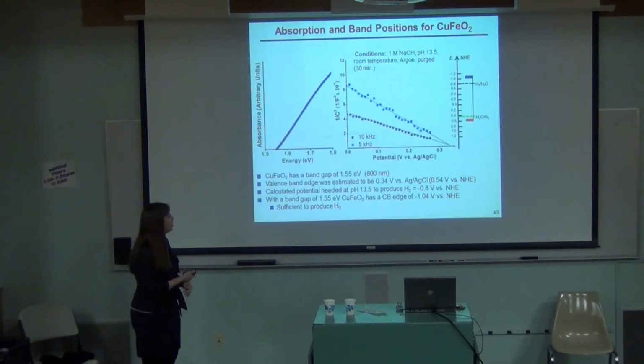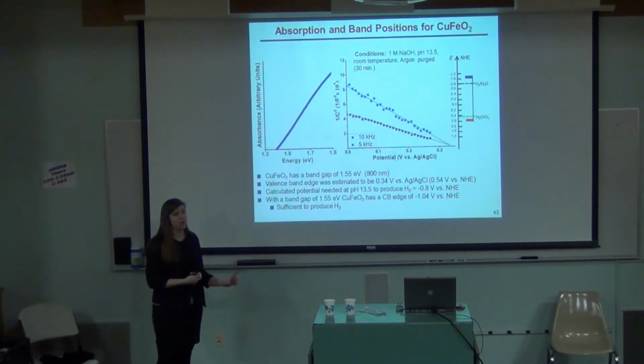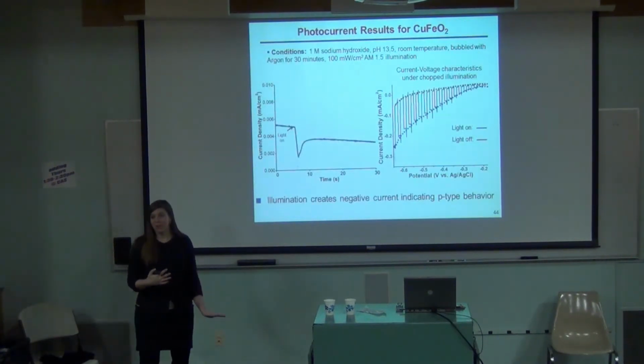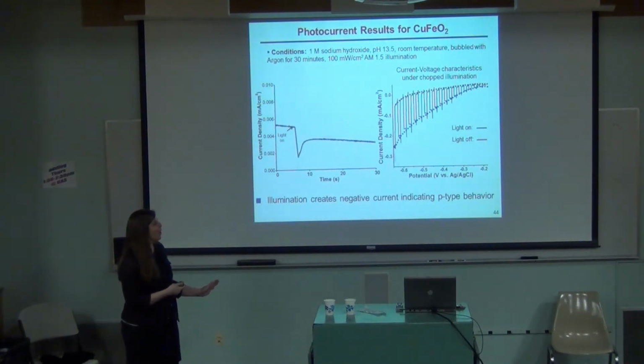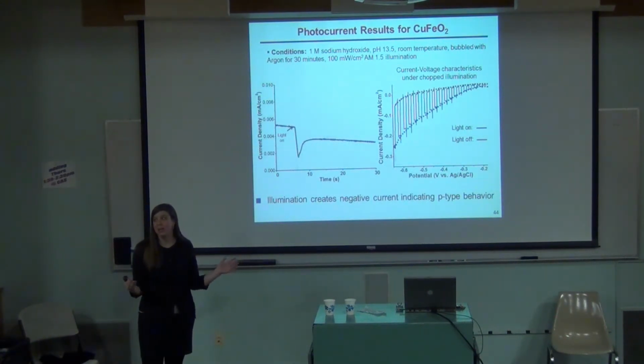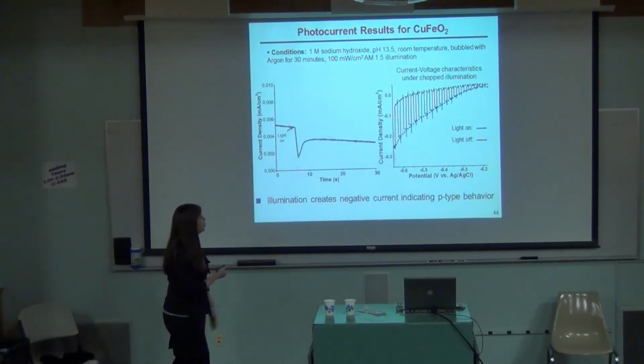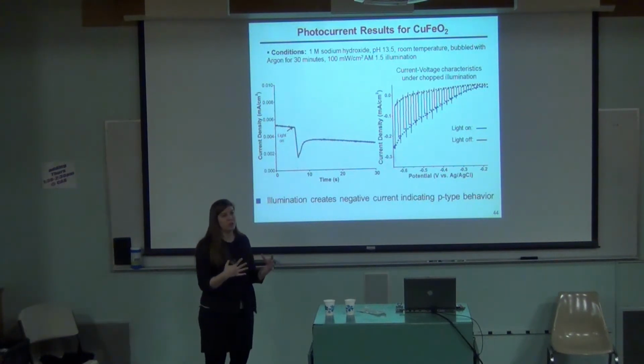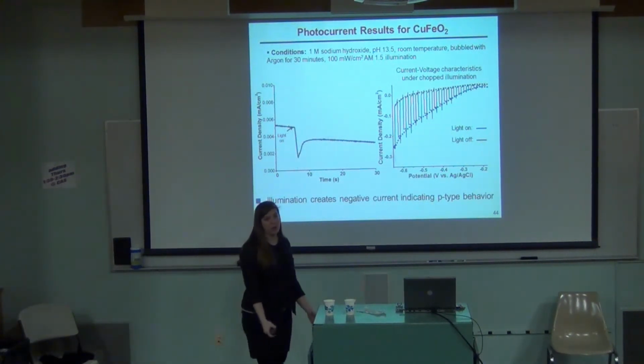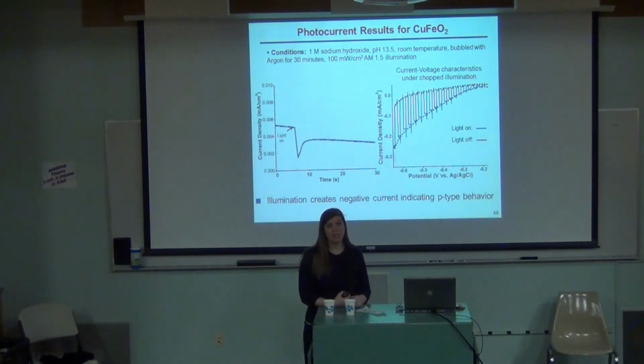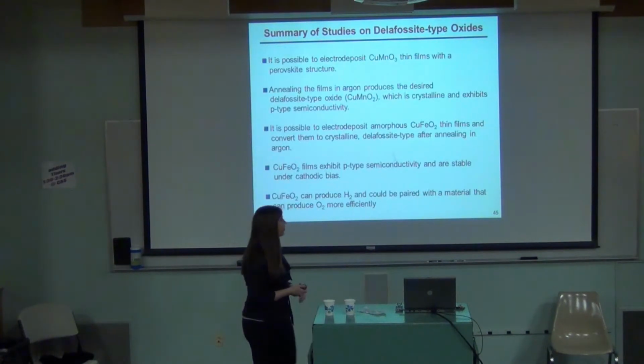But even still, with it not being that crystalline, we got a good band gap. We have good band positions that this can actually do both, so that's encouraging because it could actually produce hydrogen and oxygen, which is a great thing. And then our final test, I know that you're on the edge of your seats, we actually didn't photoreduce our film. We got a pretty good amount of photocurrent, the same amount we were seeing, that 0.2, with our copper oxide in its best, most efficient, utilized way that we could possibly make it. And already with not much effort being put into detailing how to make this structure in the best possible way, we're already getting the same efficiency as the copper oxide. So that's encouraging, and means that likely with some improvements and further study we could get even better efficiency, hopefully up to 1 to 2%, and it is p-type.